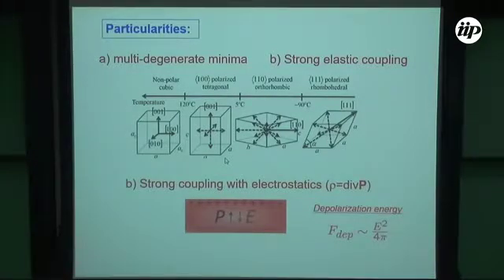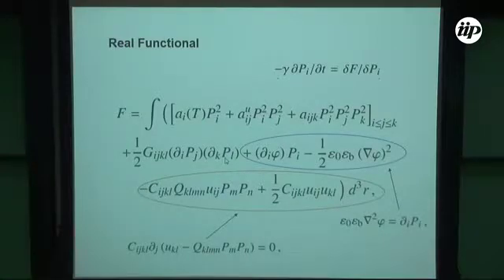So if we take into account all of these phenomena, we can write a more realistic type of Ginzburg-Landau functional that describes the situation. Now, the order parameter has multiple components. For instance, here it's not even 3 components. So we shall have at least 2 fourth order coefficients, 3 or 4 third order coefficients. So we should play with all of this degeneracy. Now, since our objective is to consider the non-uniform state, we should have the gradient coupling term, which for a cubic lattice will be 3 different gradient terms.